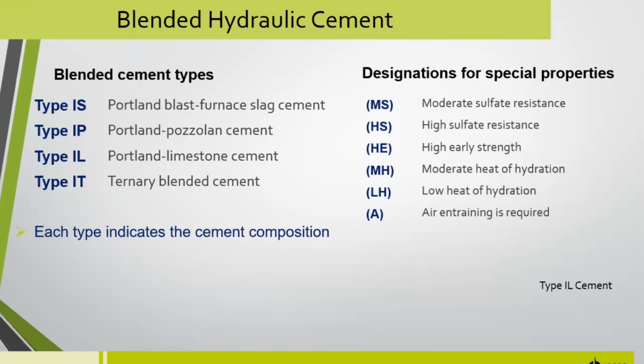And so when you're looking at your mill report, you may see some of these, and I'll get into the naming just a little bit further here in a minute, but obviously an MS would be a moderate sulfate resistance, HS would be high sulfate resistant. So in terms of equating it to a C150 cement, if you had any of these on the left and you're combining that with a designation for an MS or an HS, then the thought would be you'd use those where you would use a type 2 or a type 5 traditionally.